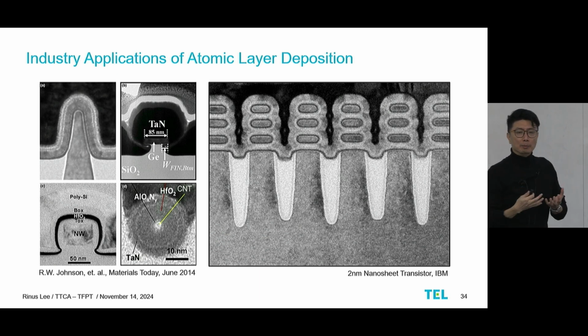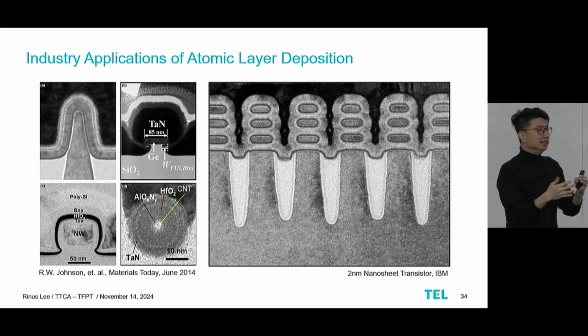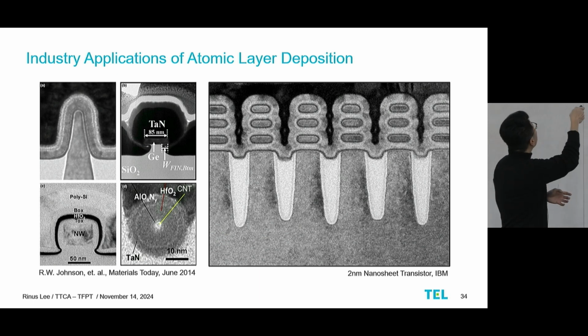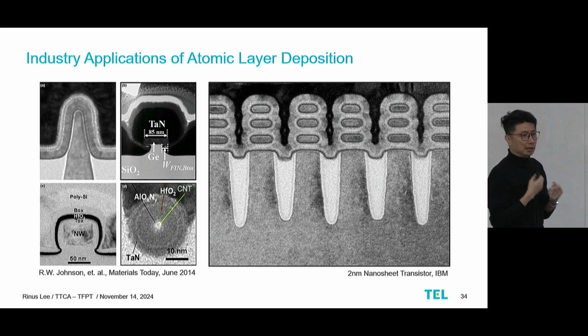If you are not using atomic layer deposition, for example, you are using a directional deposition method, which means the reaction with the surface is not self-saturating, you would not be able to get the film conformally on this surface, because you could imagine, let's say you have a deposition technique with your material coming down in this direction itself. So it will just land on these directions, and of course it will land on the side of this fin itself, but it will not be in such a conformal manner, which means it will not be such precise process control in terms of the angstrom level.